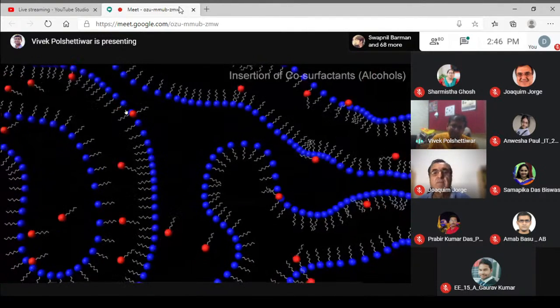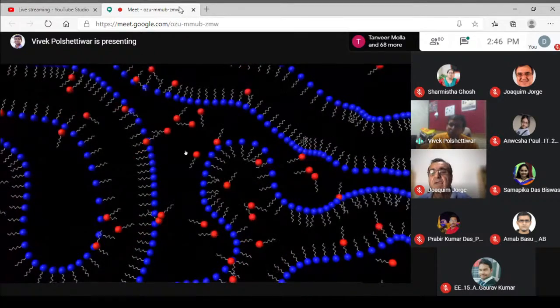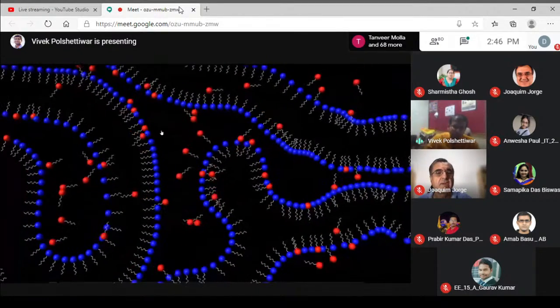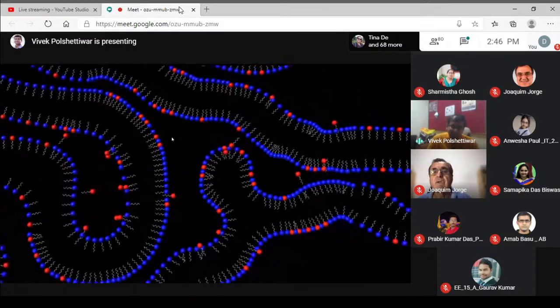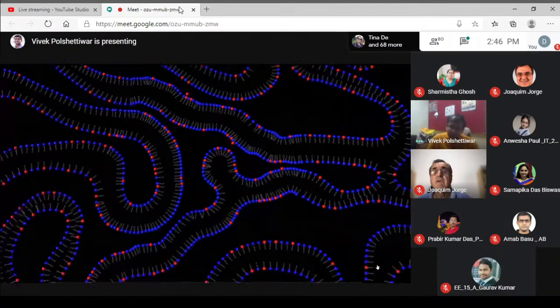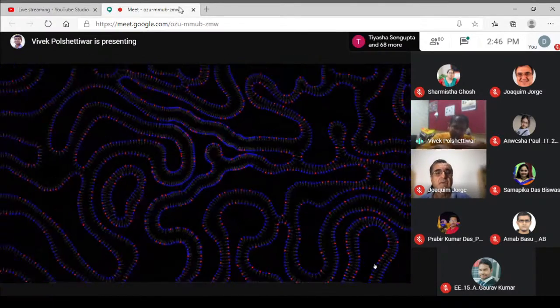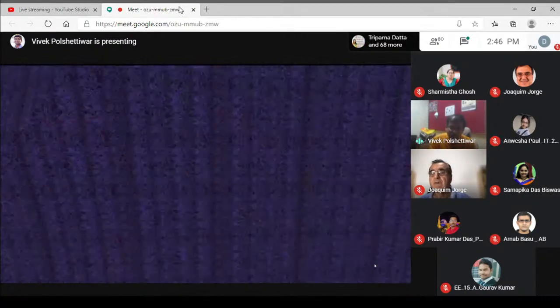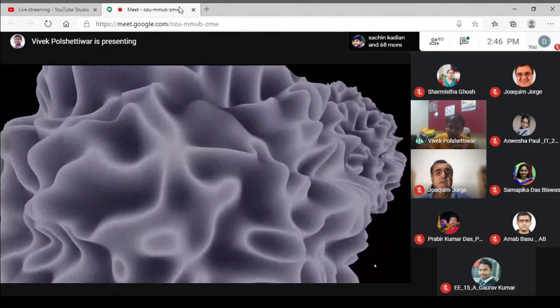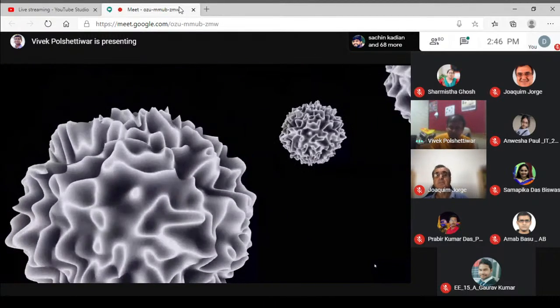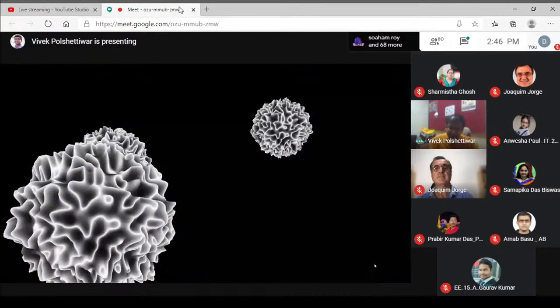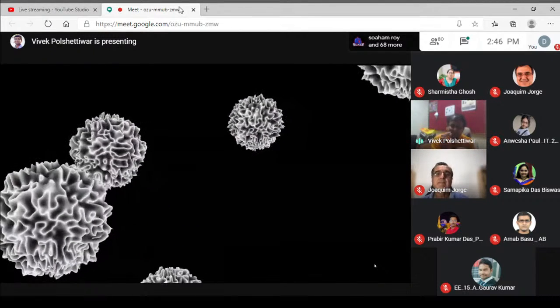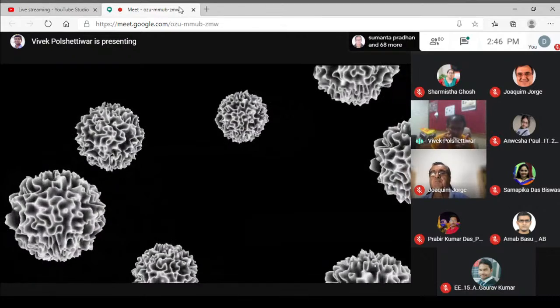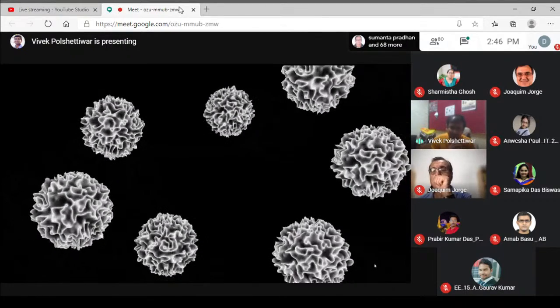To minimize the repulsion between these quaternary nitrogens, we added one more co-surfactant, say pentanol, having this polar OH, the red ball, and again the tail, and you stabilize those interfaces. Now what we observe is that these lamellar phases are not floating flat in the water or the solvent, but they are in the form of a droplet, a bicontinuous microemulsion droplet. Bicontinuous because we have water and xylene solvent, and these droplets are made up of just CTAB, toluene and xylene, and some amount of pentanol.